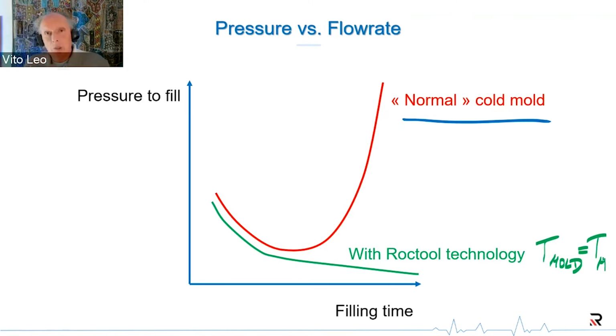Okay, in this case you have absolutely no frozen skin. You have no melt cooling near the edges, and that will give you this constantly decreasing pressure, so you can go as slow as you wish. The processing window is now infinitely wide. Now obviously that's not reasonable, because despite the efficiency of induction heating, you can't really bump your temperature that high. Technically you can, but it wouldn't be a great idea in terms of cycle times.